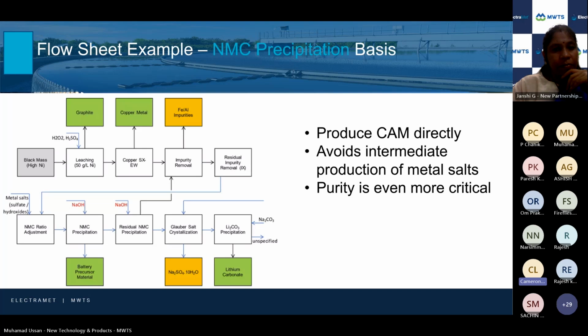If you look at the copper SX or the impurity removal, you could use less energy there and not be as strict, you don't have to hit the removal contents then because we can do it downstream. So it's more of mixing and matching what is the right flow sheet for what they want to do. And the ElectraMet system is really flexible and can tie into really any flow sheet, and we can help you optimize, how can you, again, maybe use less chemicals up front for the first step of bulk removal, so you don't have to hit purity requirements from that. So it's all about optimizing the flow sheet and finding what's the best solution at the right operations.